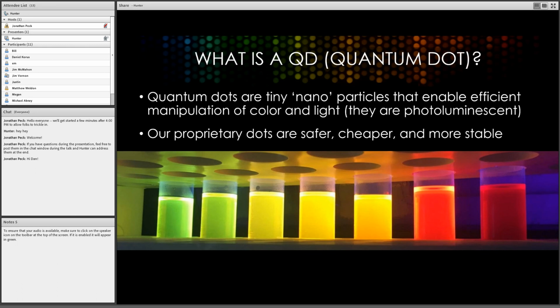And this concept isn't new. It's been around for about 35 years or so. But what we've developed was a safer, much lower cost, and more stable version. And it turns out there's one more really important property for this application, which is that they have a large intrinsic Stokes shift, which means they don't absorb their own luminescence very strongly. So that enables you to guide the luminescence through the material over, say, a sheet of glass over a square meter.